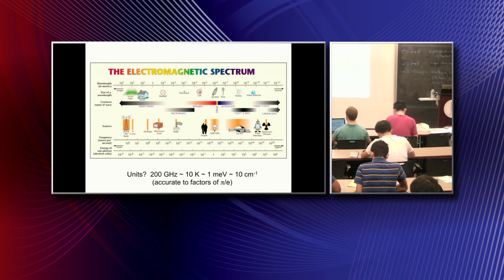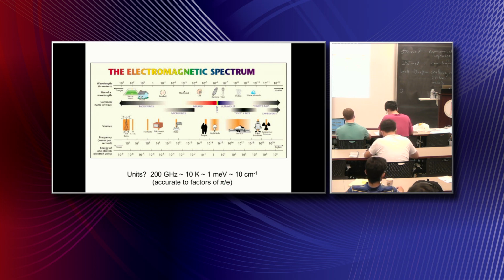Say 0.1 milliEV to say about 5 milliEV. That's the superconducting gap in conventional superconductors, things, let's say, like niobium or lead or aluminum, which we think are reasonably well understood. But of course, these are the materials which are used in many of these kinds of interesting composite superconducting systems, like the topological nanowires that we were just hearing about. Right? So important to keep this in mind.